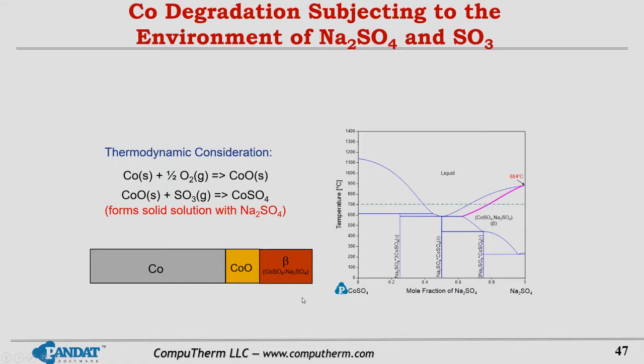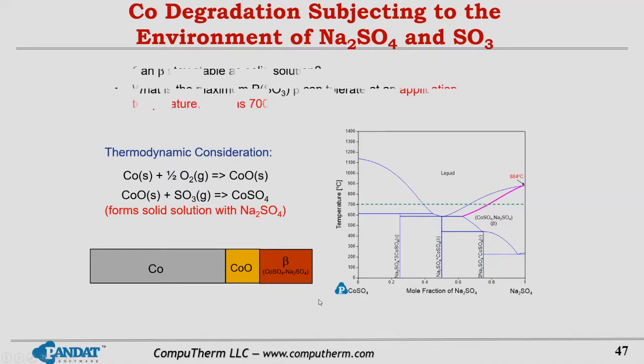Now the question is, if I want to use this material at 700 degrees C, how stable is the beta phase? If beta phase is stable, then this material is probably safe. And what is the maximum SO3 partial pressure the beta phase can tolerate at this application temperature?